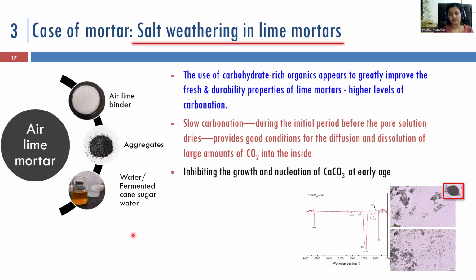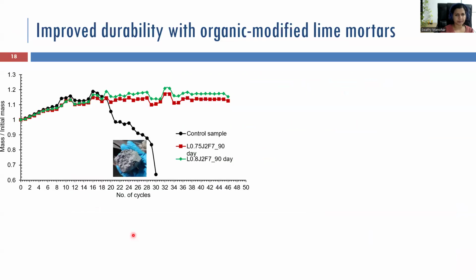This is a light microscopic image of the fresh sample, where you can see calcium hydroxide particles surrounded by a layer, due to the absorption of the organic additive into the system, that would prevent initial nucleation.